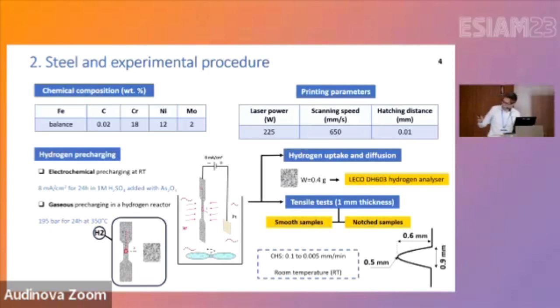We have two different specimens. The thin samples were used to evaluate hydrogen uptake and diffusion by means of a LECO hydrogen analyzer, and the tensile specimens with 1 millimeter thickness were used to evaluate hydrogen embrittlement susceptibility by means of smooth and notch specimens with this geometry. Here we can see the applied crosshead speeds. We applied from 0.1 to 0.005 millimeter per minute, and tests were conducted at room temperature.